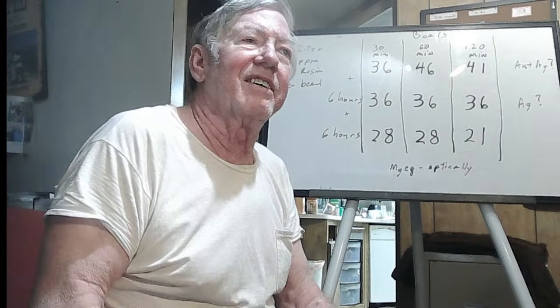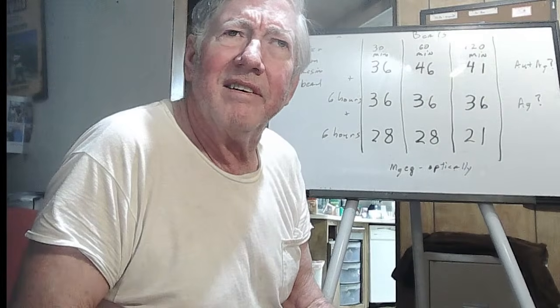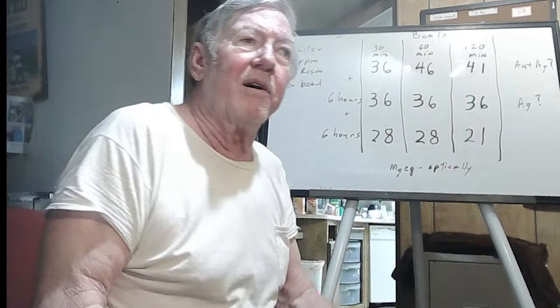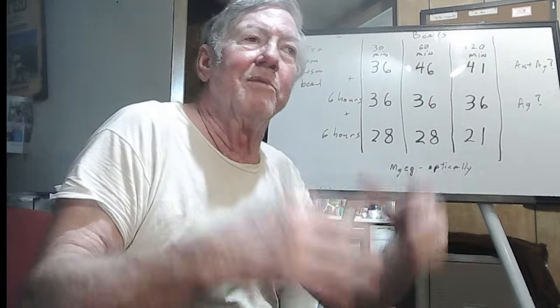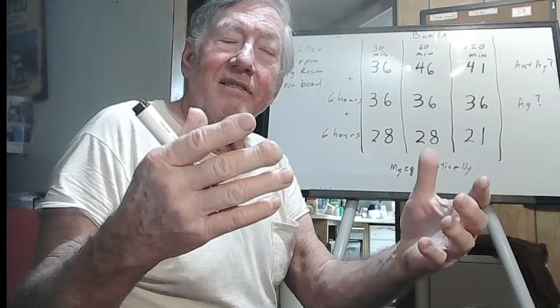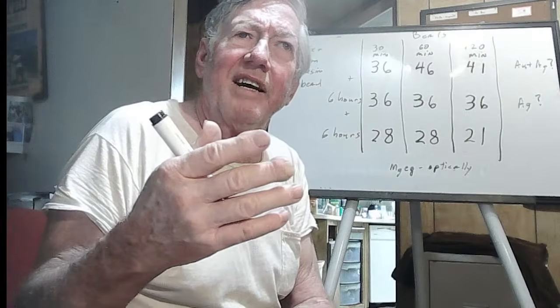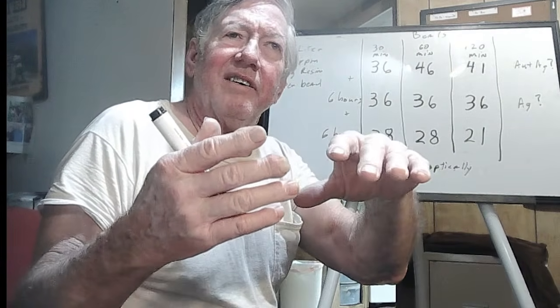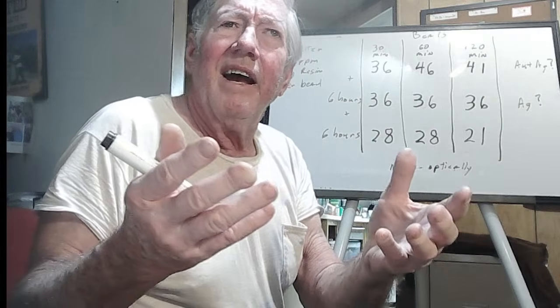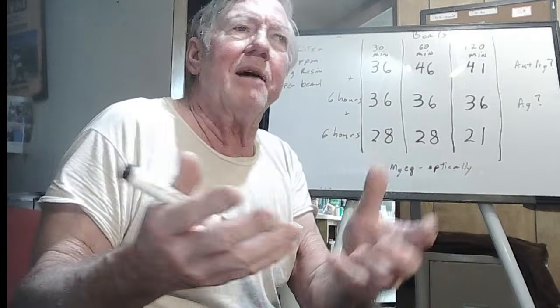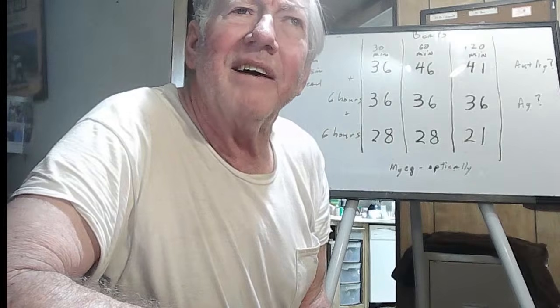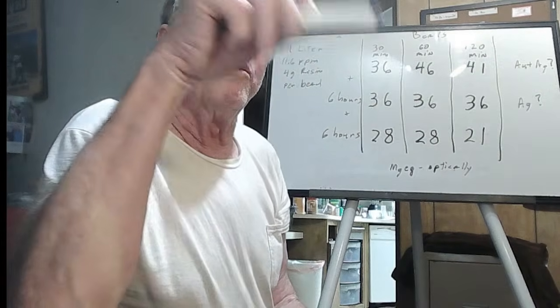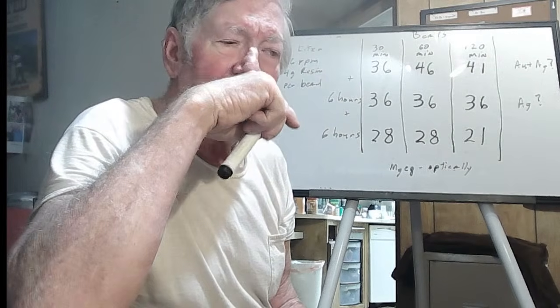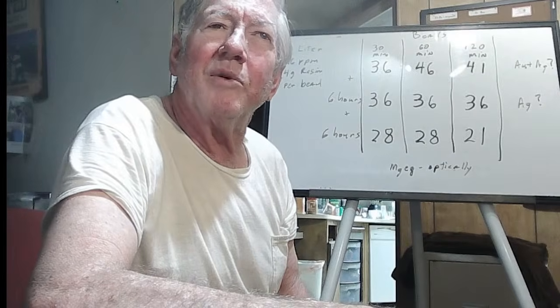Resin and pulp, on the other hand, is just not going to get that high a loading factor. There's equilibrium reactions. If you have, say, 100 parts per million, you're only going to be able to load so many parts per million in the resin. As the solution level comes down, there will be an equilibrium, and therefore you will stop absorbing out of it. With a packed bed column, you don't have nearly that much. So this is the sort of thing where I'm trying to figure out what the best way is.